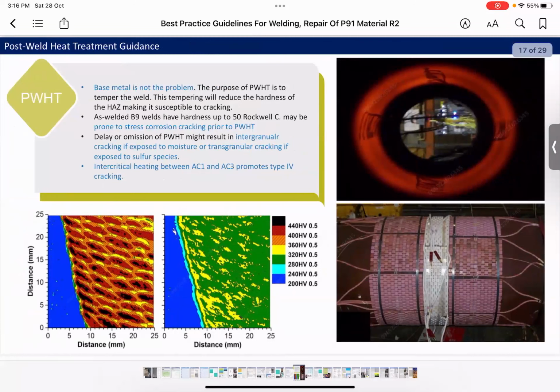For PWHT, so why are we doing PWHT? It's not because of the base metal, it's the weld metal. So the as welded P91 material has a high hardness of 50 Rockwell C. So it has to be tempered. And as you see in this graph, this is the hardness of the untempered martensite. It's in the range of 400 to 450, whereas after heat treatment, it goes down to 250 to 300.